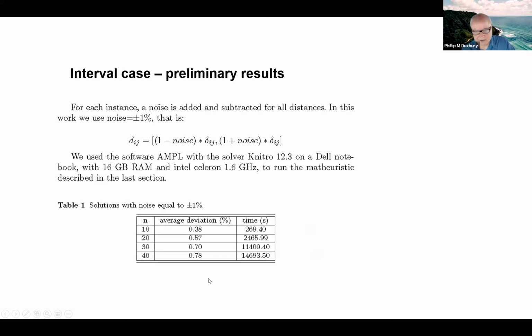the computational time taken is increased quite dramatically. Despite that fact, he was able to get to 40 atoms in a not unreasonable amount of time. And I think this is very promising, as there's a lot of things we can think about doing to improve the speed of this algorithm and the number of atoms to which it can go. I also want to add that the errors typical of PDF distances are of the order of 1%. So this is already in the range that's interesting for the problem we started out being interested in. So I think this is a good basis for future work.